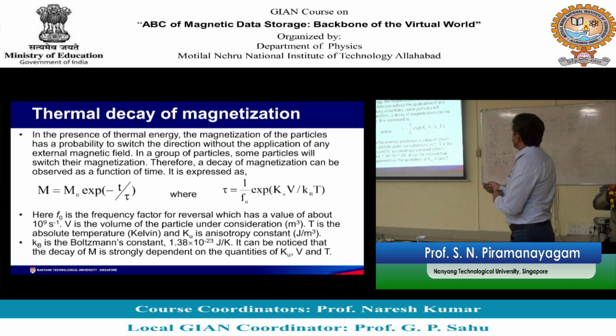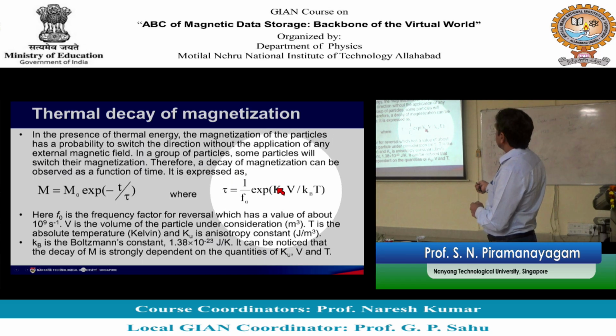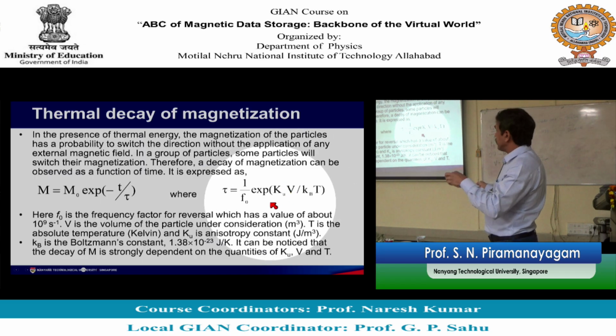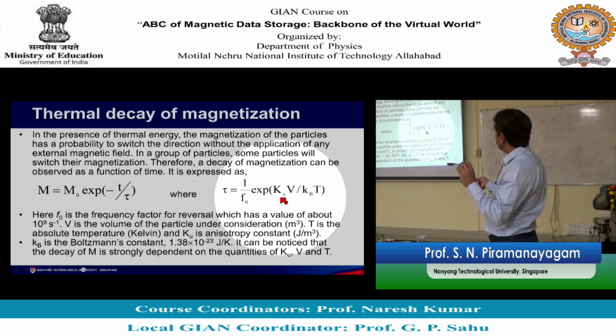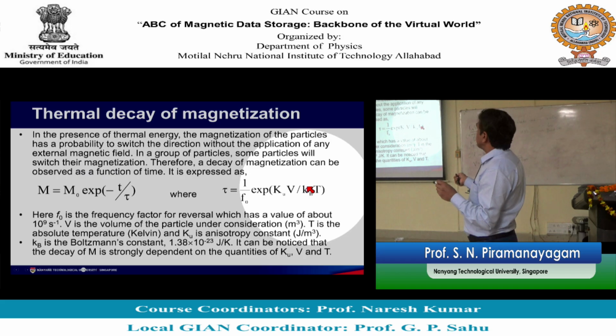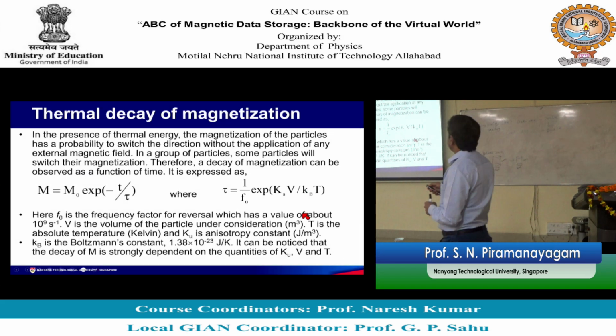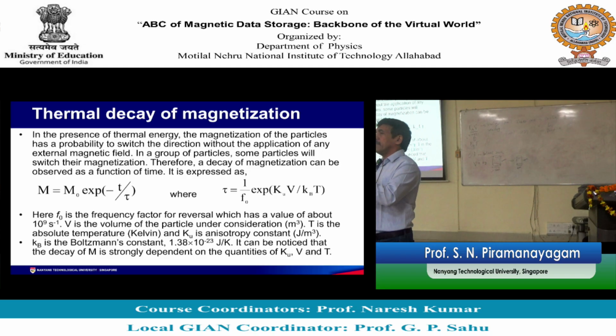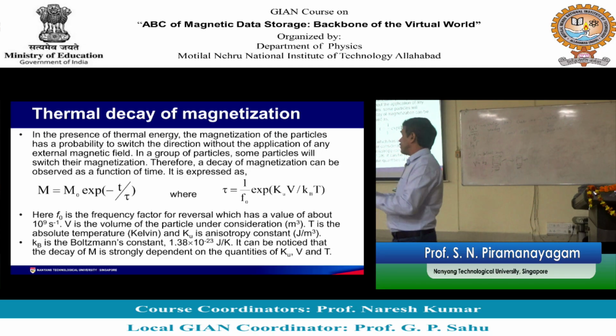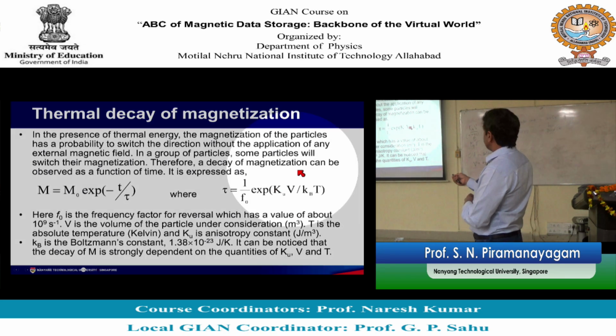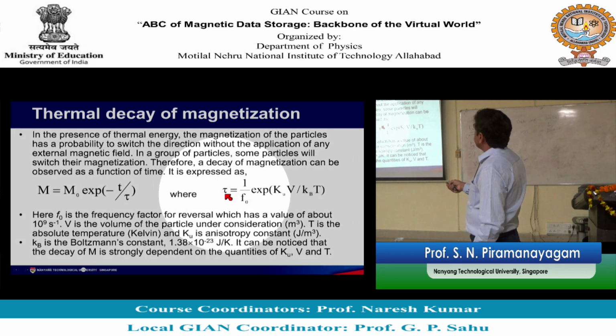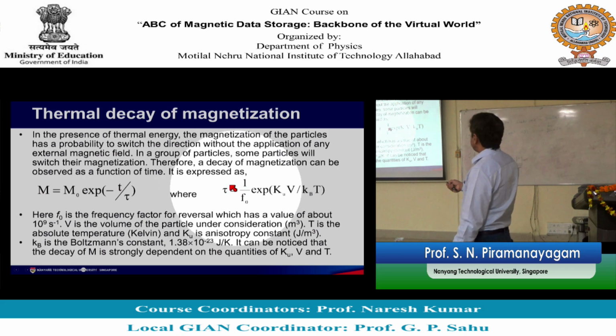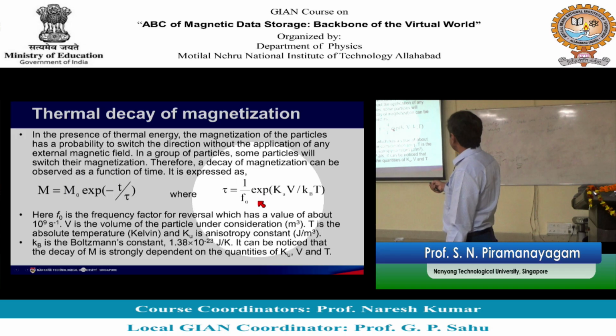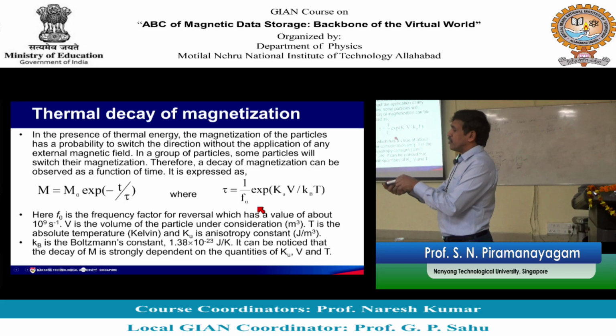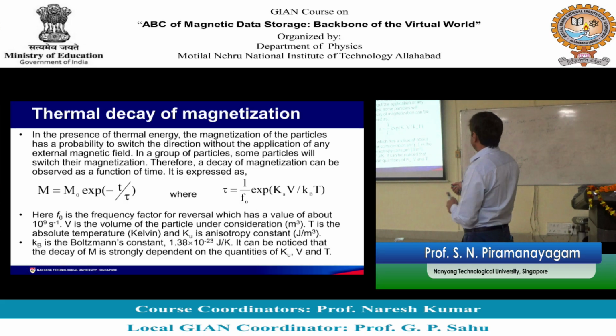So, two energies compete with each other. KUV tries to keep the magnetization in the direction that you have set it to be. KBT, the thermal energy, tries to disrupt it. When there is a thermal energy, the magnetization will probabilistically attempt to change to another direction. These two energies compete with each other and this results in a lifetime tau. This f naught is called the frequency of attempt, how frequently the magnetization attempts to go to another direction.